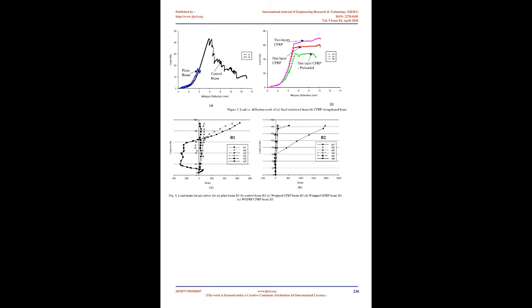Beam B3: the preloaded concrete beam strengthened with 1 layer of CFRP fabric failed due to yielding of steel followed by rupture of fabric and crushing of concrete at midspan. After failure, flexural cracks are observed in the beam, while shear cracks are not observed.